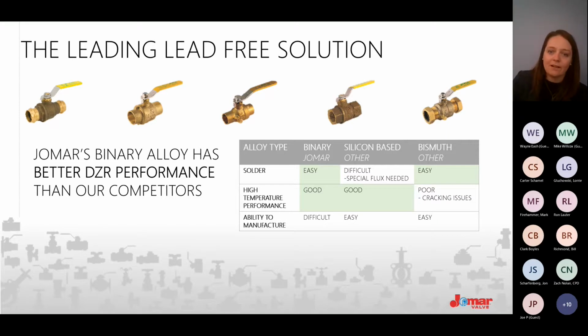Another issue that was occurring in the field is that some manufacturers increase their bismuth content. Bismuth is very similar to lead. It's right next to it on the periodic chart. However, it can have a negative interaction with a lead presence in an alloy. So as a result, being worked on at higher temperatures, it led to cracking issues in the field. We did not have that issue because we did not increase our bismuth content.